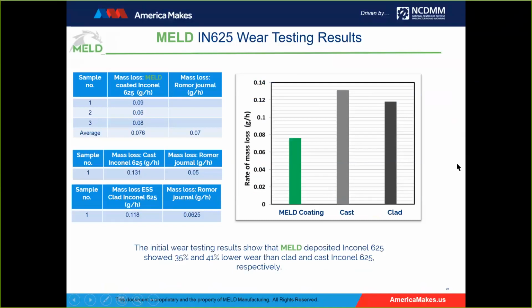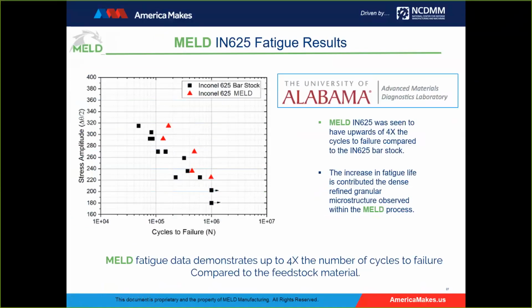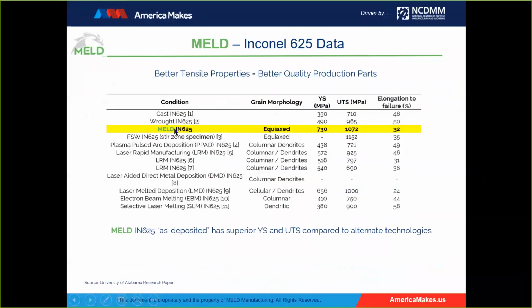Fatigue, up to 4 times the number of cycles to failure compared to the feedstock material. Really good fatigue data. Here's our Inconel as deposited compared to cast and wrought and other additive manufacturing technologies, and you see a significant comparison of our yield strength and ultimate tensile strength compared to a cross-section of other technologies.